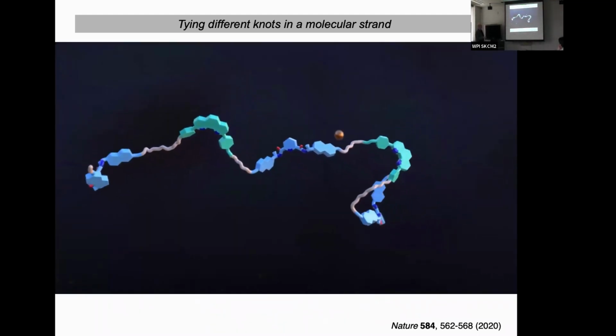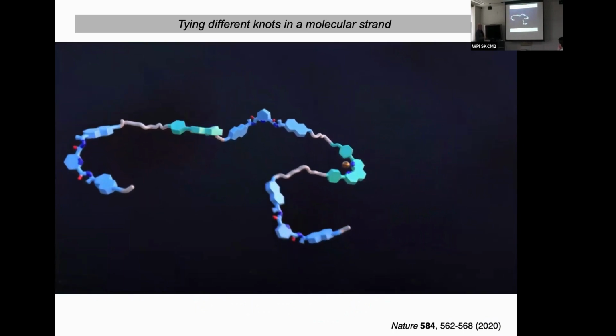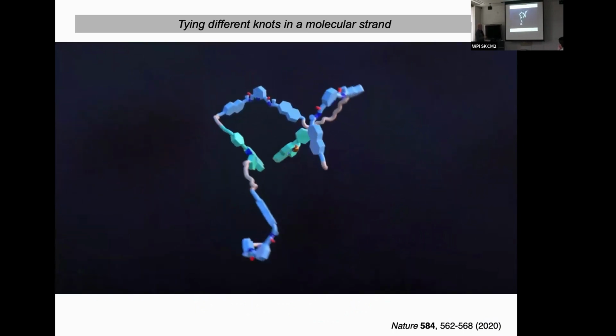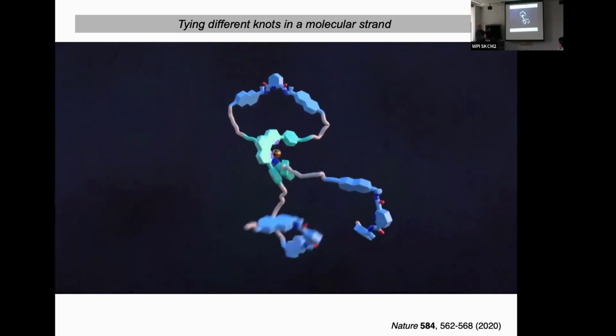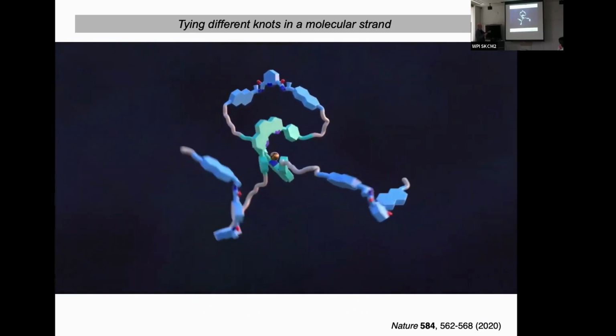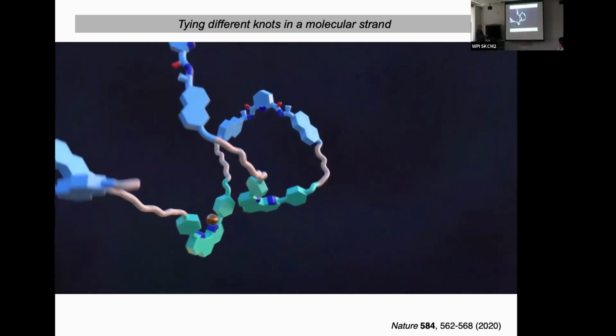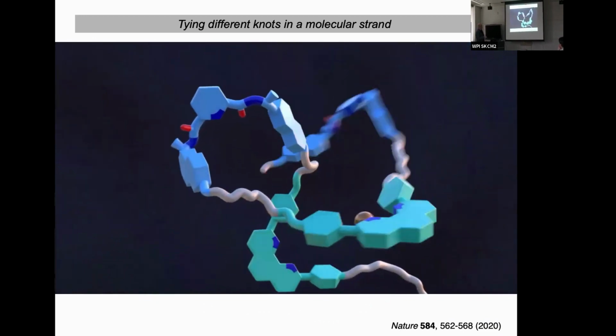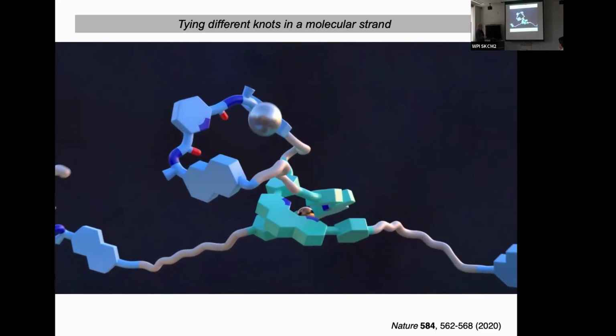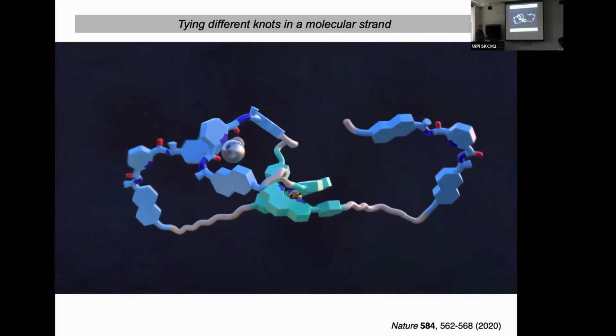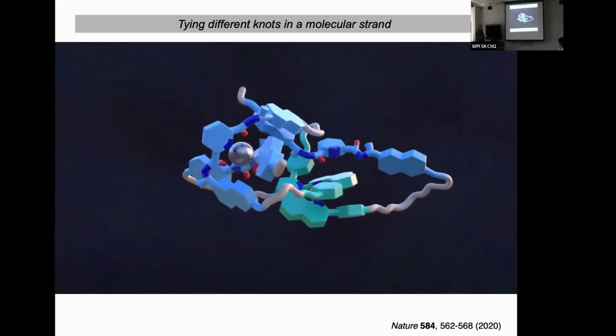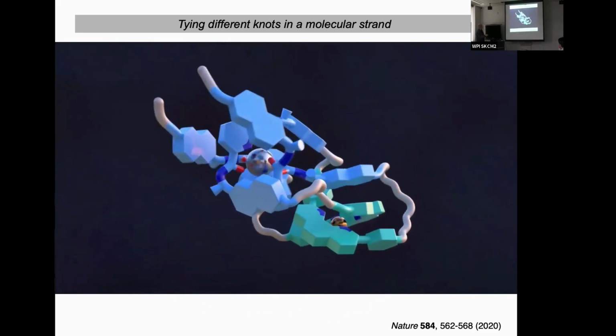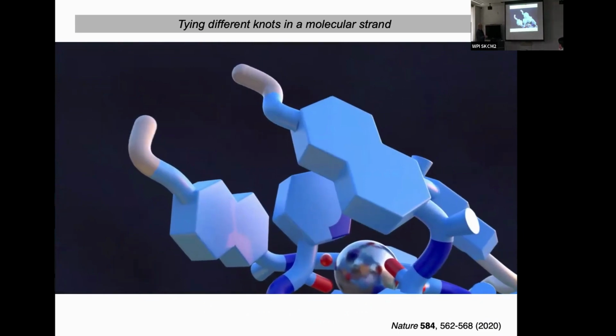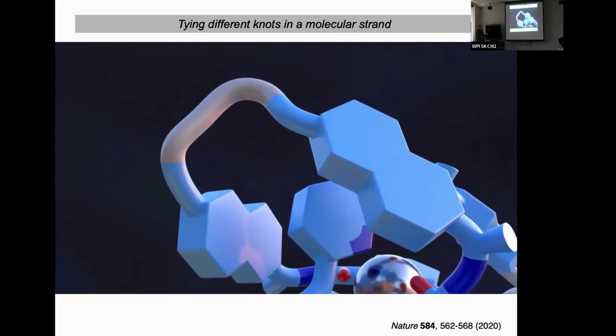So this is the strand. The phenanthroline units will bind to the copper, and they can bind either way round, or these ligand strands can switch so that they're this way round. But when they're this way round, here we've got the chiral groups around the lanthanide group. So this can only thread one way, and they thread through the copper loop.